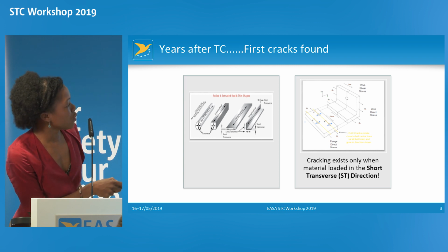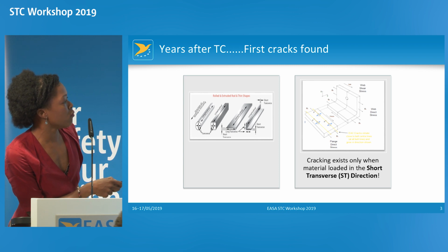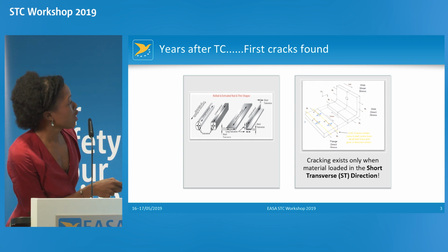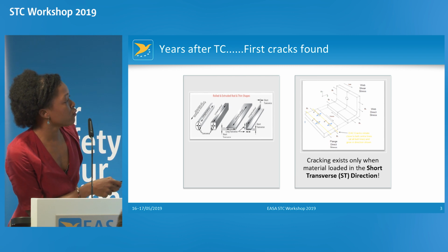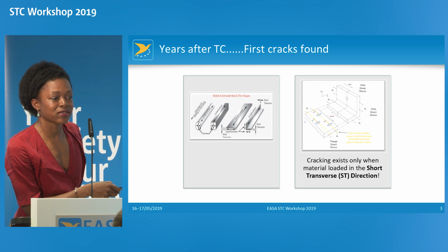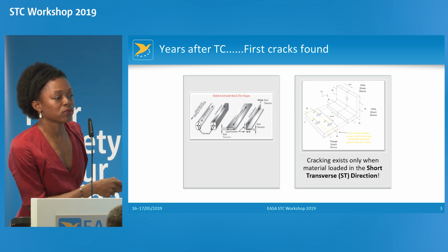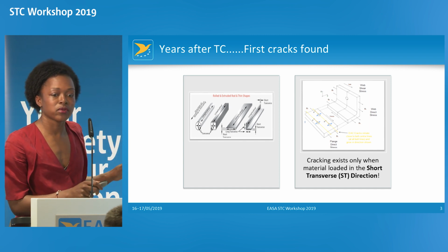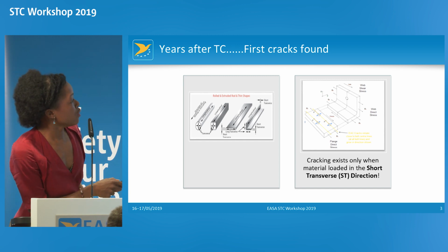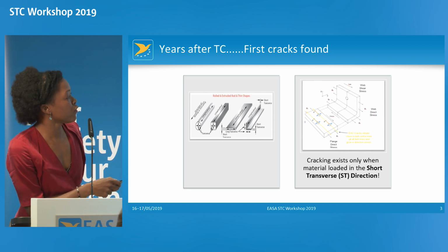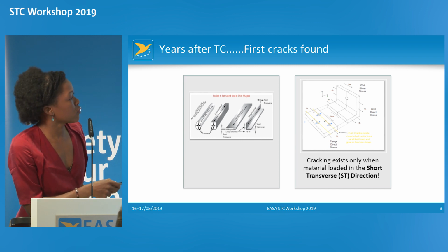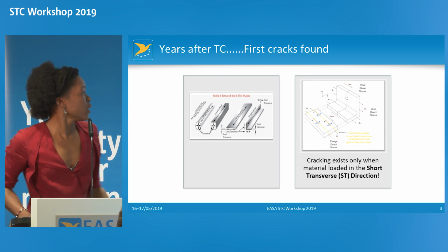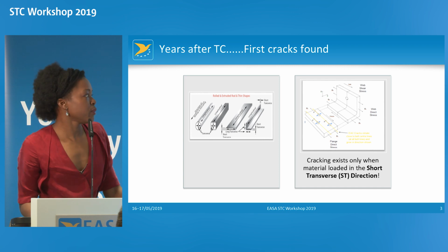On more conventional shaped parts, let's assume that this is a spar, or it can be a frame or a stringer, no matter if you have L shapes or C shapes, the cracks appear starting from fastener holes, and they appear in the direction parallel to the stress, whereas under fatigue they are supposed to develop in the perpendicular direction. But this has nothing to do with fatigue. Starting from the fastener holes, cracks develop in the direction of the yellow line, going from one rivet to another, while the prone direction for crack growth is this one. So this was quite surprising at the very beginning.